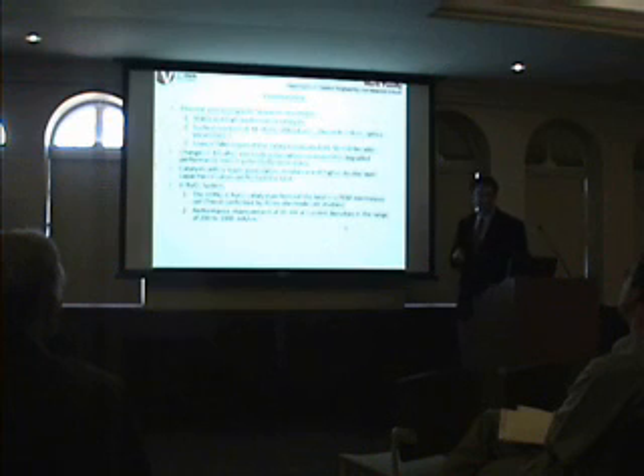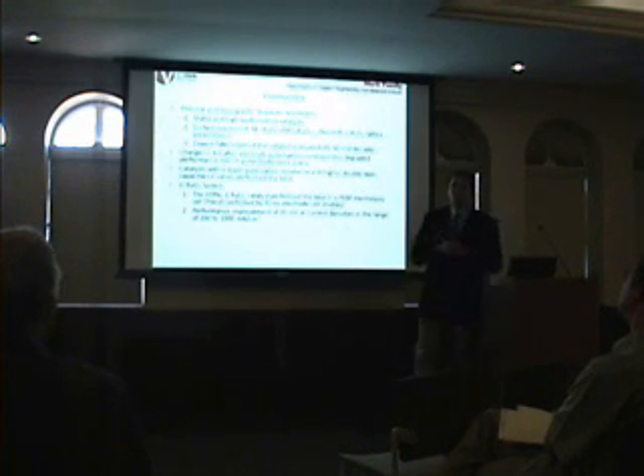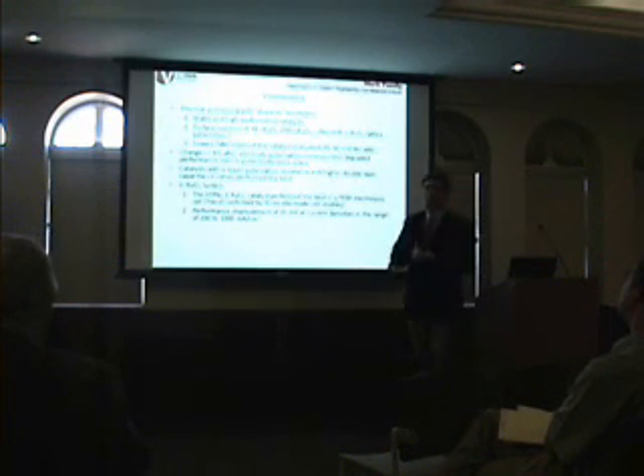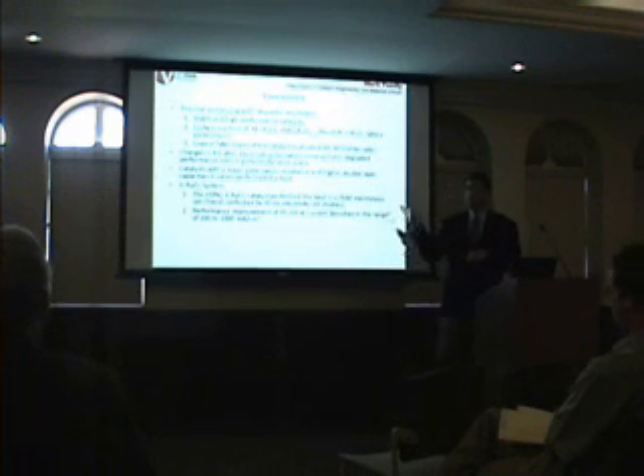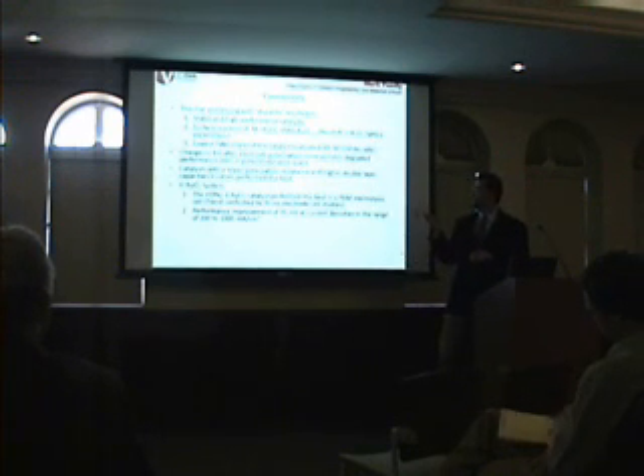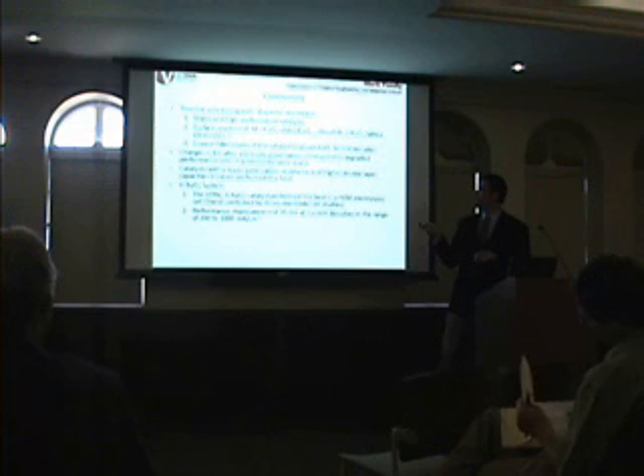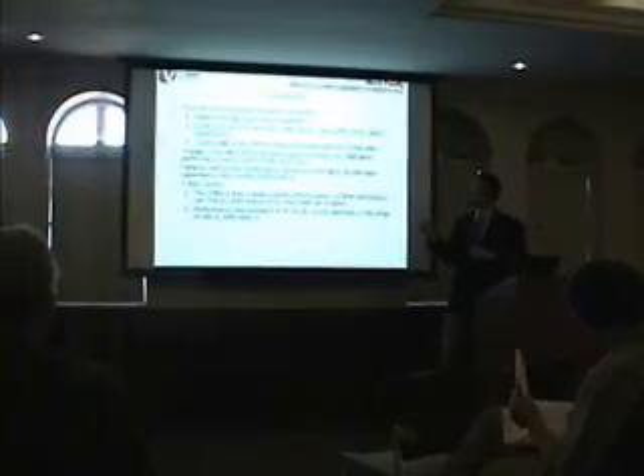Yeah, let's explain that. So concluding, we actually showed that our thermal processing with dopants resulted in what? It resulted in a stable high-performance catalyst. One thing that I forgot to talk about, and I'm going to kick myself for that, was that if you looked at the X-ray diffraction patterns, there was no shift in the ruthenium oxide, which essentially meant that we're most likely having a surface reaction. The electrochemistry is all about reactions at the surfaces. So that's not too surprising.